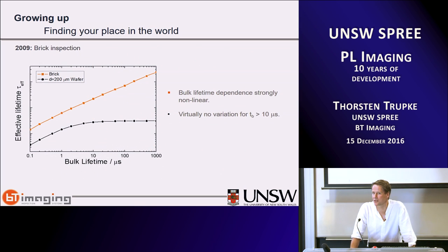The next application is on silicon bricks, and this is where Bernard has contributed a lot during his PhD, and now together with Daniel in current work that we do as part of an ARENA project. Brick inspection has one major advantage over wafer inspection, and that is that you can still measure bulk lifetime. This graph here shows the effective measured lifetime as a function of the bulk lifetime for a 200 micrometer thin unpassivated wafer and for an unpassivated silicon brick. And you can see that here, the black line saturates. Once we reach bulk lifetimes of 10 microseconds or more, the effective lifetime on the wafer essentially has no information about the actual bulk, because it completely becomes dominated by the surface recombination.